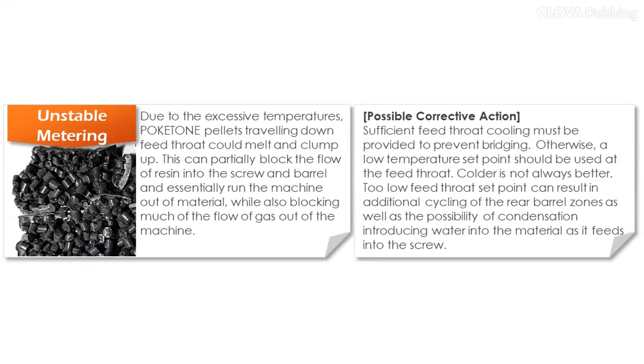Due to excessive temperatures, polyketone pellets traveling down the feed throat could melt and clump up. This can partially block the flow of resin into the screw and barrel, and essentially run the machine out of material while also blocking much of the flow of gas out of the machine. To prevent this issue, sufficient feed throat cooling must be provided to prevent bridging. Otherwise, a low temperature set point should be used at the feed throat. Colder is not always better. Too low a feed throat set point can result in additional cycling of the rear barrel zones, as well as the possibility of condensation introducing water into the material as it feeds into the screw.